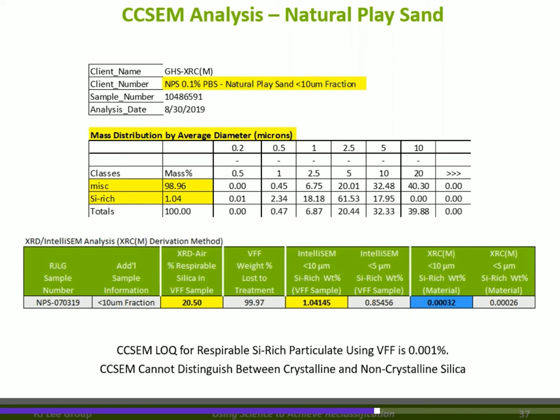This does not tell us about crystallinity, only the Si rich. But if it isn't Si rich, it cannot be crystalline silica. So we've got our XRD result. For XRD Air, we know that there's 20% crystalline silica in this little tiny fraction. From that, we now know that there's only 1% silica rich, which is much less than the silica by XRD Air. So as a result, most of that silica is bound up with other material, and it is not free and bioavailable.